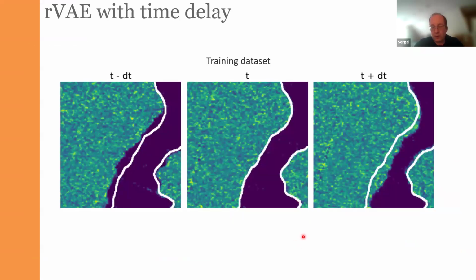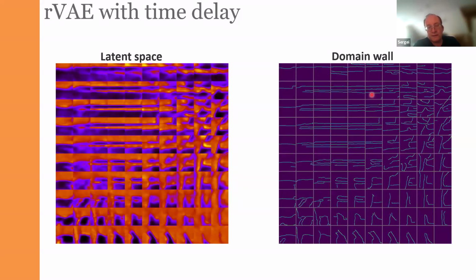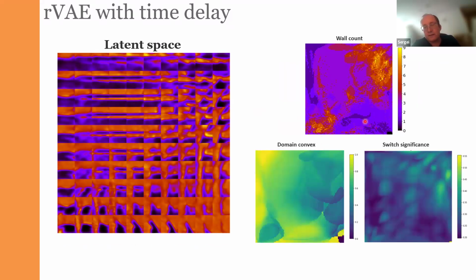We can run more complex examples where we create the descriptors centered at a domain wall observed at time t, but the patch is taken at the domain at time t plus delta t. So then it encodes the time variation. In this case, the latent space becomes more complicated. When it looks like this, I'm very tempted to say that we don't have enough data, and they start to show fairly complex structures in it. But nonetheless, we can get some idea about the properties of the domain.